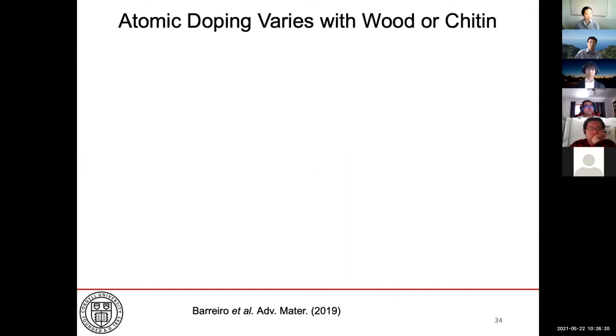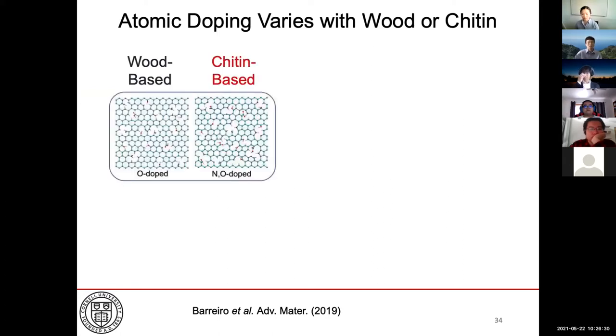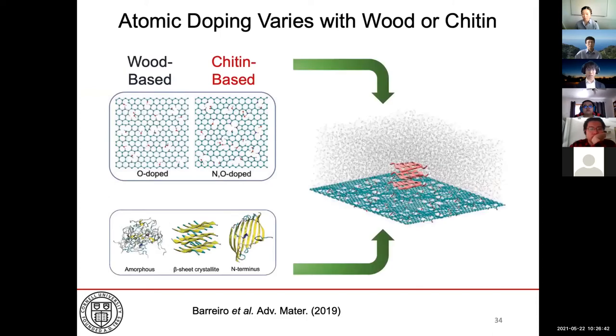And from X-ray photoelectron spectroscopy, we actually determined the structure and doping content of activated carbon, where we found that wood-based carbon is generally oxygen doped, while chitin-based carbon is both nitrogen and oxygen doped. Now, this different doping changes the binding strength to carbon. So we modeled the randomly doped carbon and the different silk structures. And then again, we applied that advanced sampling molecular dynamics method to actually determine the structural changes.